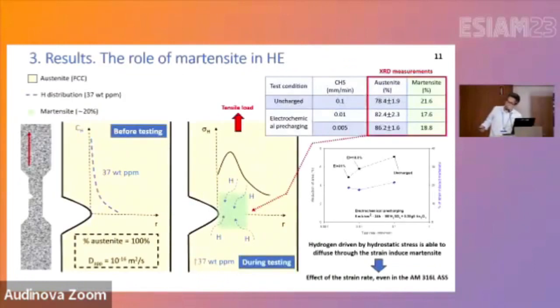Before testing, as we mentioned previously, our microstructure is 100% austenitic, and the apparent diffusivity is 10^-16 square meters per second. However, when we apply the tensile load, because of the metastable behavior of the austenite, martensite is formed mainly in the notch tip region, and this effect was revealed by means of X-ray diffraction measurements. The apparent diffusivity in the martensite phase is 4 or 5 orders of magnitude higher than in the austenite phase. So by means of this effect, and also motivated by the high hydrostatic stress existing in the notch tip region, we can say that hydrogen driven by hydrostatic stress is able to diffuse through the strain-induced martensite.